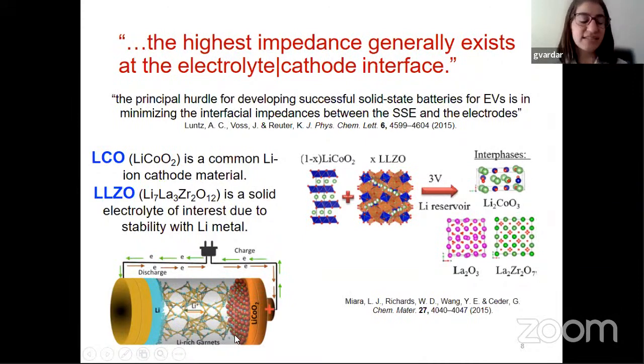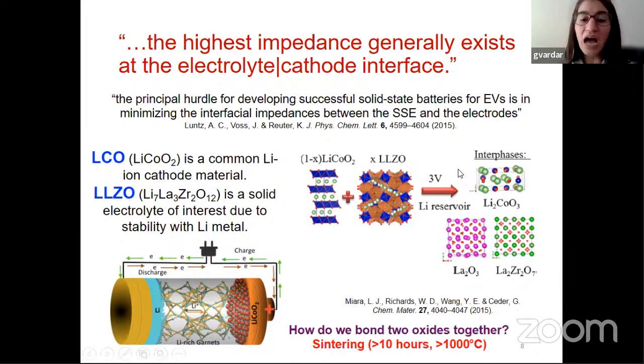And the problem with this interface is that when we put these two materials together, they make secondary phases. So they come together and they react, and these reaction products stop the lithium from crossing over. And so what we call interphases, basically. So how do we bond these two oxides together? Is that another problem? In order to bond two solids together, you need to sinter them. Sinter them meaning heat them above 1000 degrees over 10 hours. So that's a really high energy process.